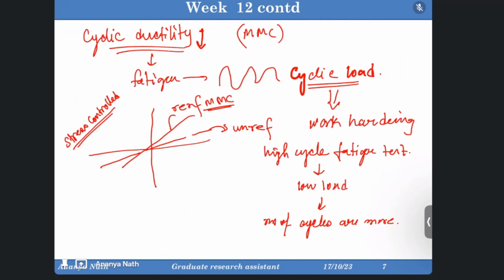hardness material. Then if I am talking about the next scenario, which is the strain control, there the things will be reversed. As the applied stress will be very high, there will be sudden breakage in all the particles, even if it's small or big. If it's small, there will be detachment, and this is how the particles can get agglomerated in one state, and the matrix can get debonded with the particles, and wherever it is getting debonded, there will be some crack initiation, and if there is some crack initiated, then the crack will grow very fast due to that high stress. So in case of strain control, the scenario is completely opposite.